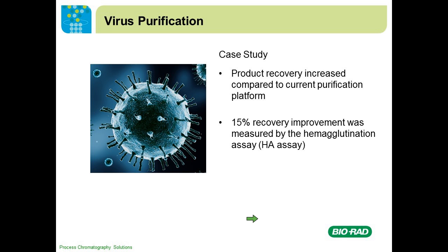And viral particle, as I mentioned earlier in the slide, the most challenging problem in viral purification is that the viral particle is so big. Even if you have a resin with a large pore, the particles may penetrate, but sometimes they are physically trapped inside the pore. Therefore, the recovery is a big issue. One of the customers evaluated our resin, and they found they were able to increase the recovery by 15%.